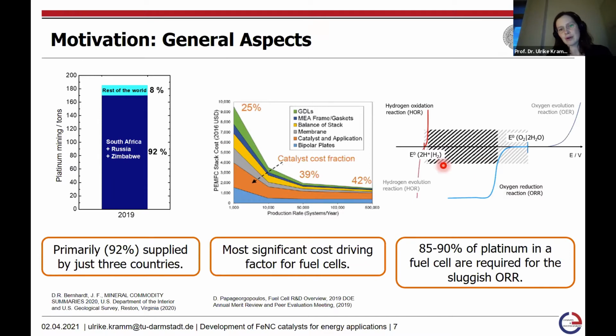This you can see, what I plotted here is the potential, and here we have the standard potential for the oxygen reduction reaction, and here's the standard potential for the hydrogen oxidation reaction. The red curve that goes up here is the real performance of a platinum catalyst material for the hydrogen oxidation reaction, and this gray dashed part here mimics the overpotential losses that you need in order to gain this current density. When you look then at the oxygen reduction reaction, and this is the same current density in terms of absolute value,